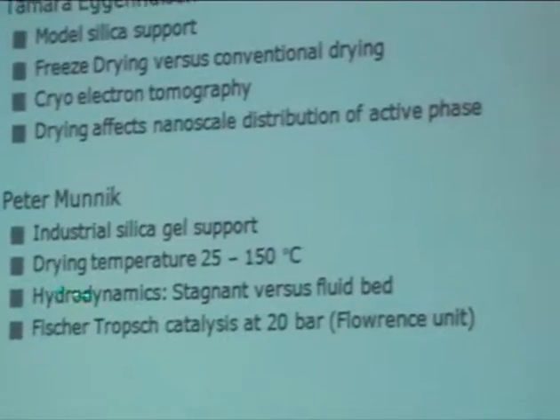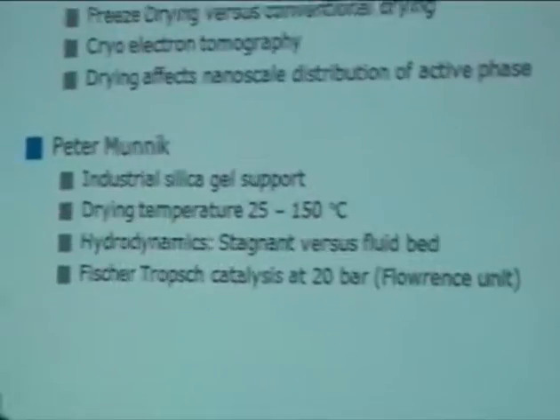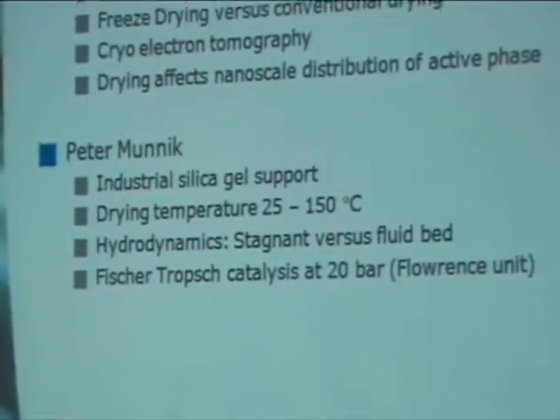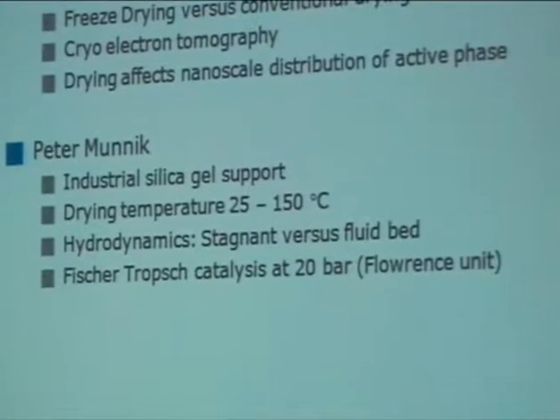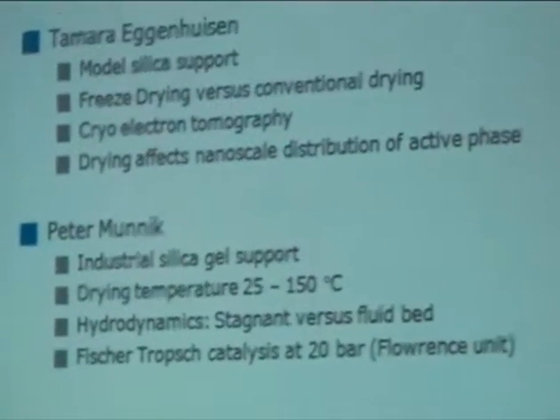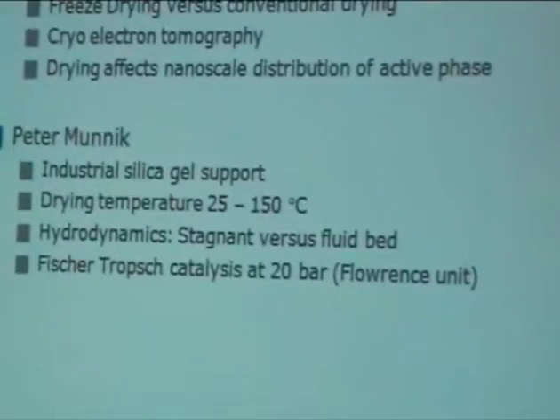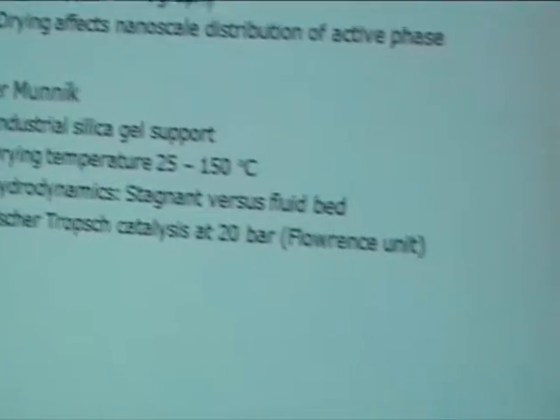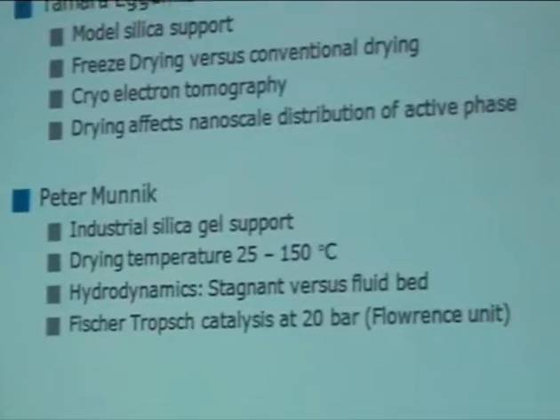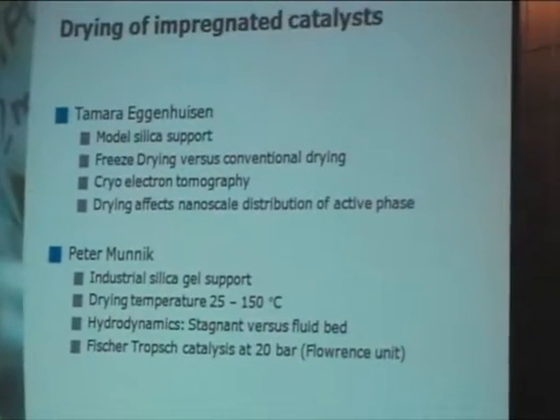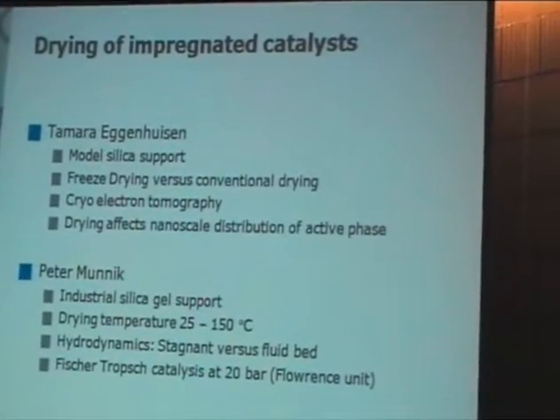but perhaps even more importantly, the hydrodynamics of the system. He moved from stagnant drying, what is usually done at laboratory scale, where people impregnate a catalyst, put it in a muffle furnace, come back the next day, and take it out. That's the drying in many, many cases. Well, we use the fluid bed, so that controls more, gets you more uniform conditions for each individual macroscopic particle. And then they measure the Fischer-Tropsch catalysis at 20 bar. So let's first have a look.